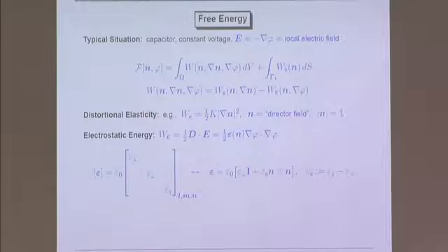The medium is that of a uniaxial crystal, so the dielectric tensor in its eigenframe has one distinguished eigenvalue, epsilon parallel, and a degenerate pair. In tensorial notation, it's most conveniently written in this way. The dielectric anisotropy is the difference between the susceptibility parallel to N versus perpendicular to N.